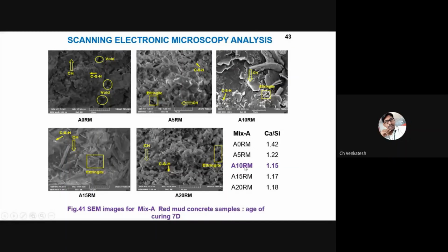But as a point of EDS also, I have conducted the EDS analysis, and I have identified that the 10% concrete has a low calcium by silica ratio. Generally, the calcium silica ratio indicates the presence of CSH. Generally, for CSH the calcium silica ratio range is 0.8 to 2.5. So if the calcium silica ratio is very low, you can call it a strong CSH gel. And if the calcium silica ratio is very high, the CSH gel is very poor. So in my study, at 10% I have got a low calcium silica ratio, and this value also supports the experimental results.